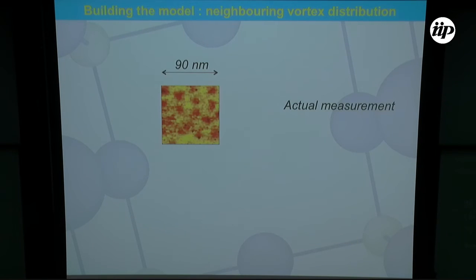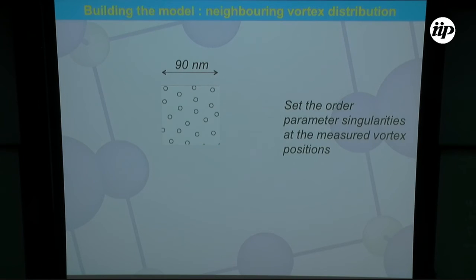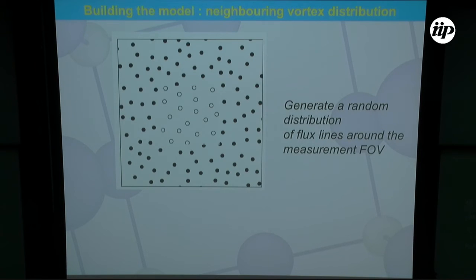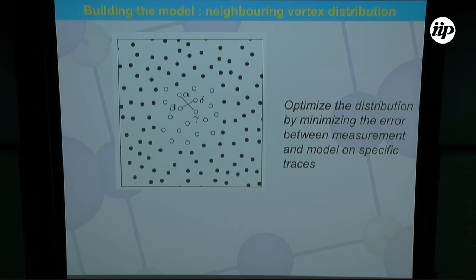So this is the procedure. We take our spectroscopic map of the vortices, which allows us to find the position of the vortices and set the position of the singularities. Then we generate a random distribution of flux lines around this field of view, and then select specific traces from the measurement. Then from the model, we calculate the local DOS for each position of the field of view of the map, and minimize the error between the measurement and the calculation.